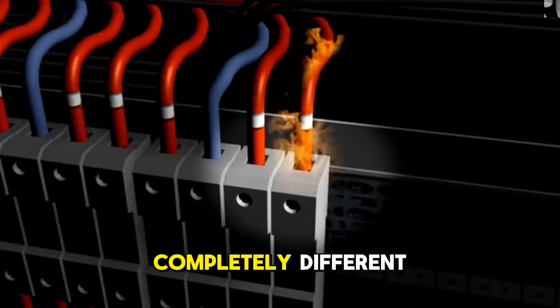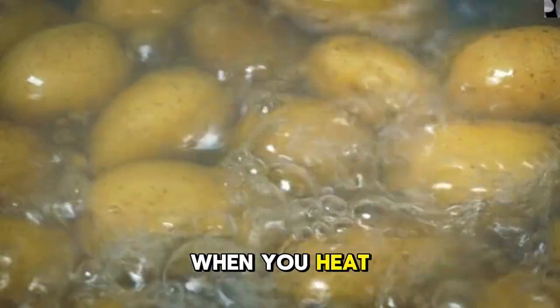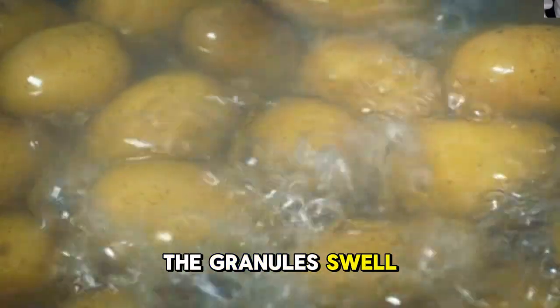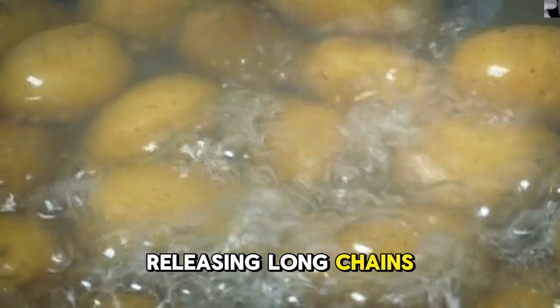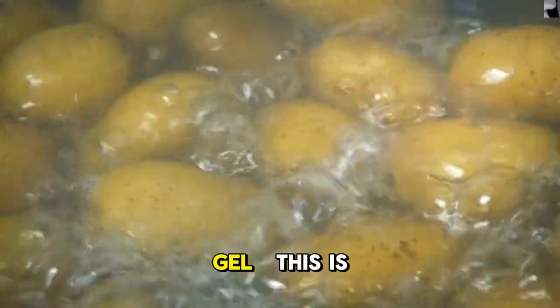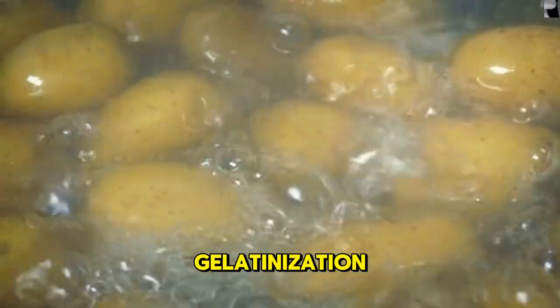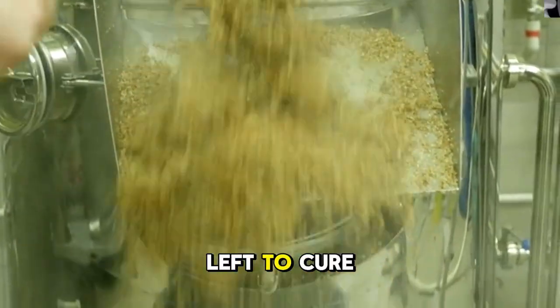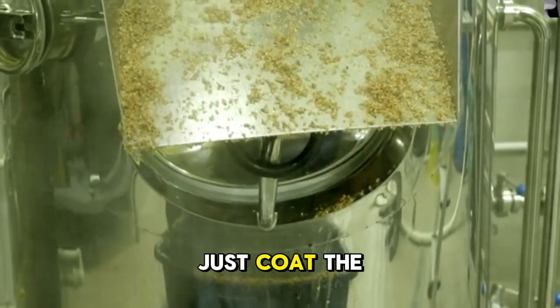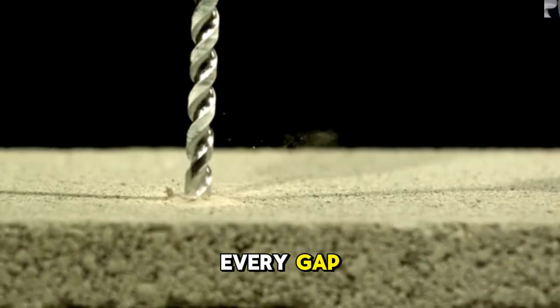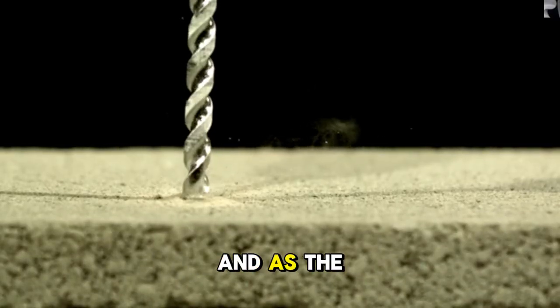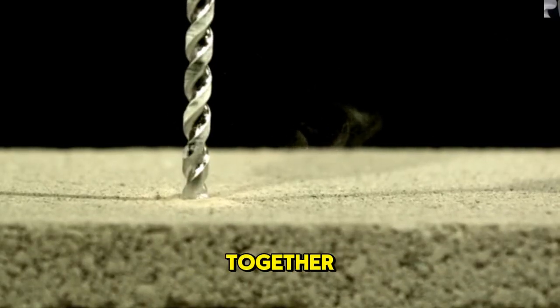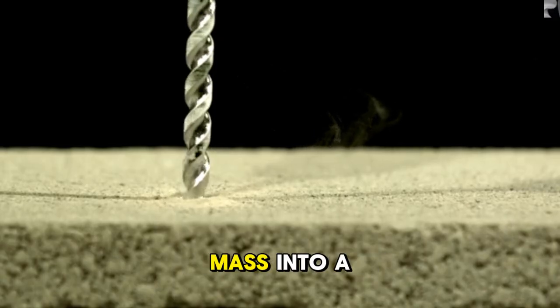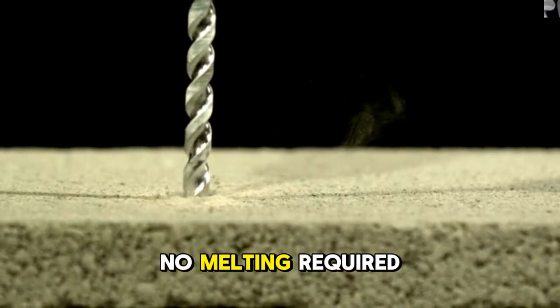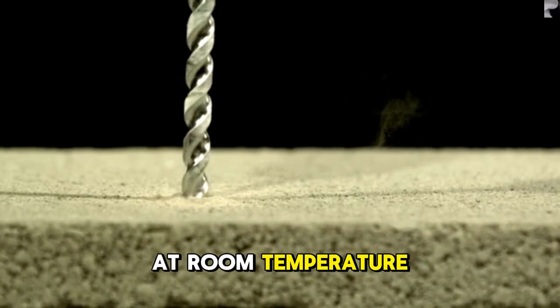Starch takes a completely different path to a similar result. When you heat potato starch in water, the granules swell and burst open, releasing long chains of carbohydrate polymer into a thick gel. This is gelatinization, the same reaction that thickens a sauce. When that gel is worked into sand and left to cure, those polymer chains don't just coat the surface. They thread through every gap between grains. And as the mixture dries, the chains lock together into a dense internal net that binds the whole mass into a solid block. No melting required. The binding happens at room temperature.